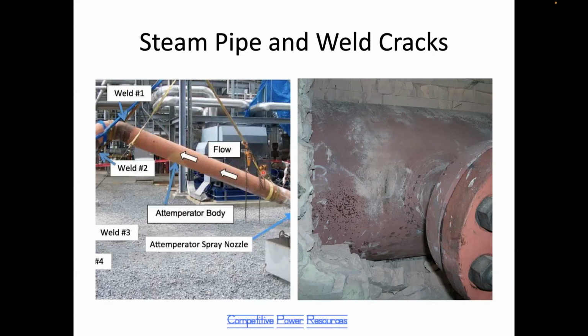The other symptom is cracking in the steam pipes. This is an Attemperator pipe. The spray nozzle is located down here, and there are 4 welds on this pipe. All 4 of these welds were cracked due to, in this case, severe overspray for a long period of time. Here's another crack at an Attemperator nozzle right here.